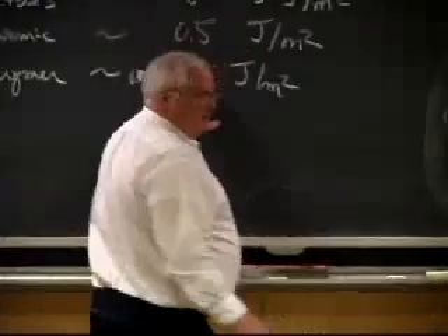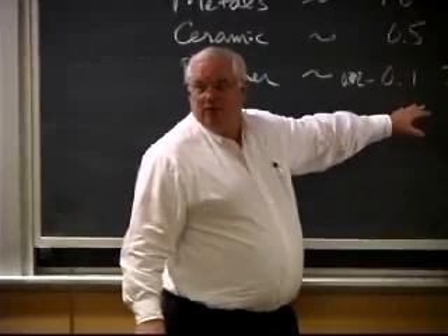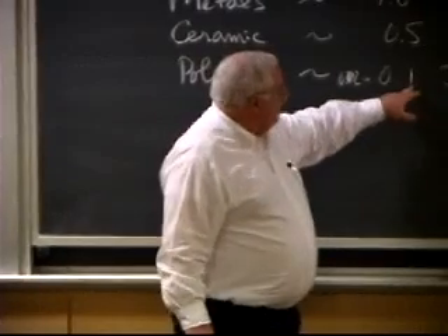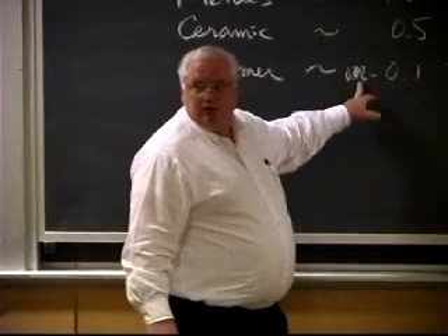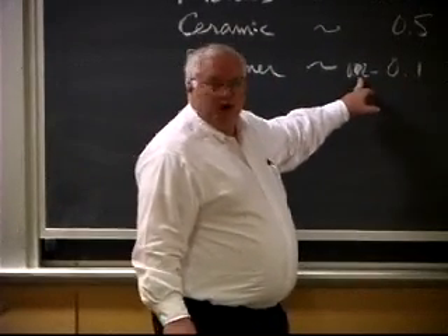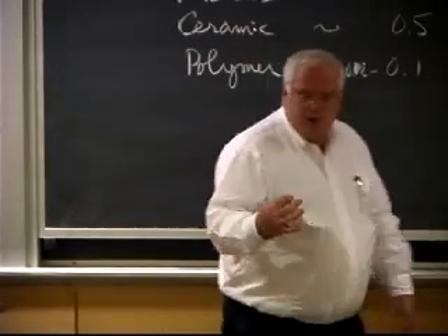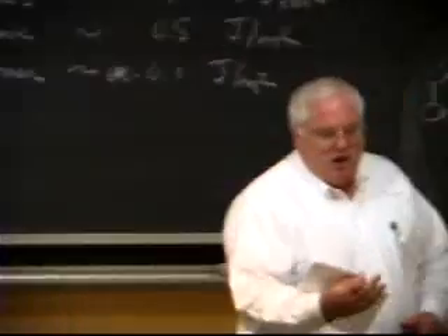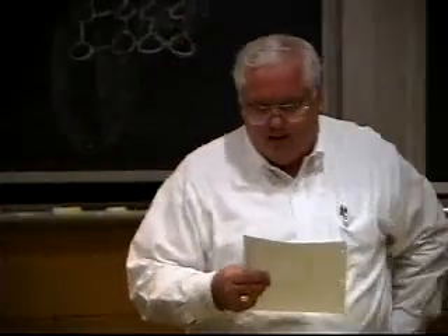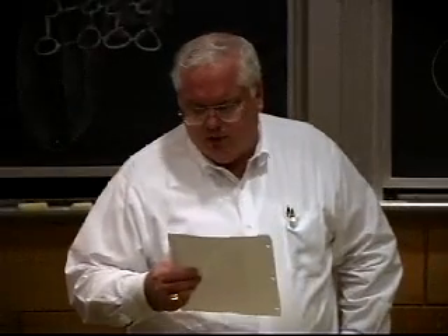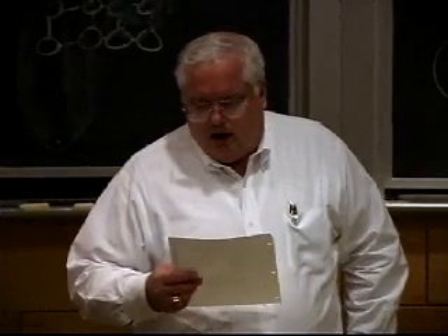Water, which is a covalently bonded molecule, right, H2O, has a surface energy of 72 ergs per square centimeter, 0.07 joules. Okay, it's hydrogen bonded. So this is actually hydrogen bonded, and this is non-polar van der Waals type of bonding down here at 0.02. Teflon has a surface energy of about 20. And I think you've been given a handout on that.